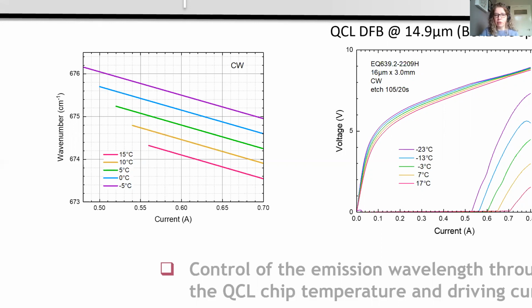You get a continuous tuning range that you can sweep by changing the current. For the quantum cascade laser, in this particular example, you can see when the chip is at 15 degrees, that's the red line on this chart here. So when it's at 15 degrees, you can continuously sweep over one wave number, and that's along the red line shown in this chart. This is achievable because of the narrow line width of these lasers.